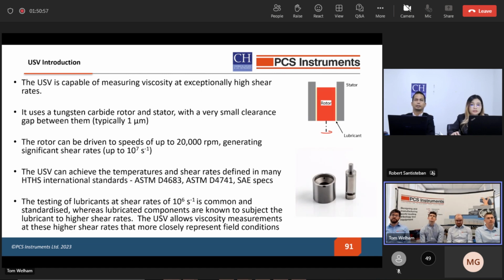So to allow testing at these extreme shear rates, a precisely machined rotor is spun up to 20,000 RPM inside a stator, with a gap of just 1 micron between them. And that allows the USV to meet the specified conditions of many standards, which are listed here.